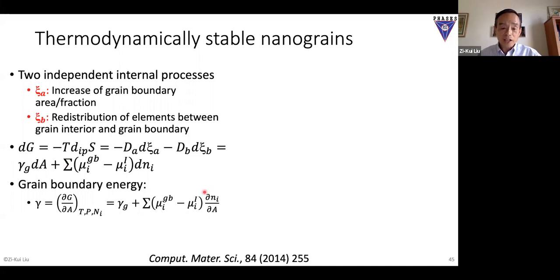Segregation, of course, was studied before - that's called Gibbs adsorption. And this one was also studied before - that's grain boundary energy. But we don't put them together; we studied them separately. But if you put them together, the combination can make this term zero, because this is positive and this could be negative. That's what happened.